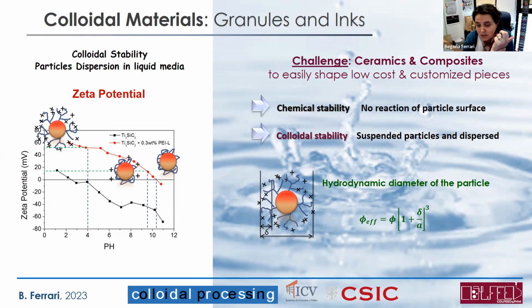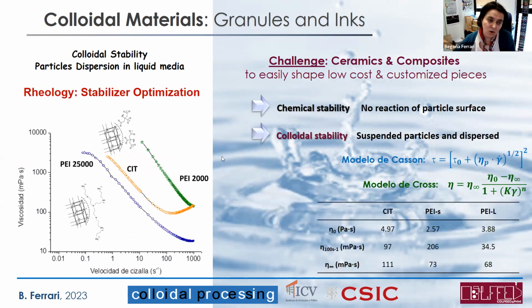This colloidal chemistry that we study here is influencing a lot how the suspension or the ink is behaving in rheology, in the rheology test, and also in the way we pack and the process we use. So if we measure the viscosity with the shear rate, having the same particle, independent of the kind of stabilizer we use, we have completely different rheology in our suspension. We can use the rheology models, Casson and Cross, for example, to calculate the main parameters of these flow curves.